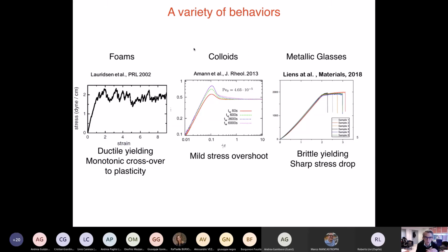If you consider model systems which are more macroscopic, in which the microscopic sizes are quite big, you have the behavior that you see on the left, the one of foams, for example. If you look at the stress-strain curve, when you strain the system, when you deform the system, the stress increases, and then you reach a plateau and start to have some erratic behavior around a certain value. So the system goes from an elastic behavior to a plastic behavior. It starts to flow beyond a certain value of the strain and of the stress. This is the typical ductile behavior, or ductile yielding, that you have in, for example, foams or granular systems.